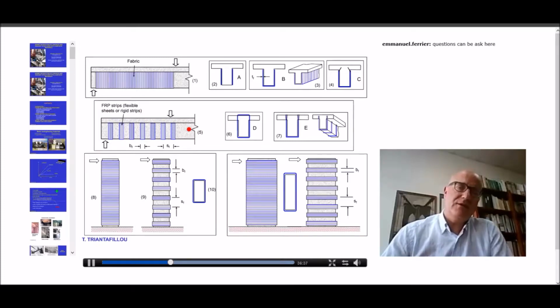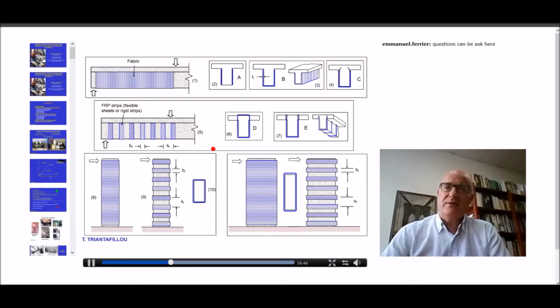In this series of sketches here, you see typical configurations of FRPs used in shear strengthening. For example, in the case of T-beams, we have a number of options. This is what we should avoid. This is the so-called two-sided jacketing. In this case, we simply bond FRPs on the two faces, on the two sides of the webs. The other option is to use the FRPs all around the webs. This is a so-called three-sided jacket. This is far better than this one here, because we have better anchorage, better bond conditions of the jacket. This is even better, to anchor the three-sided jacket inside the slab using spike anchors. I will get back to this in a couple of minutes.